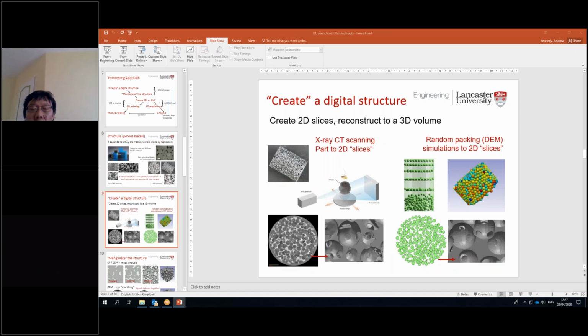So we can create digital structures in a number of different ways. What we found is a good approach is to use different methods to create 2D slices, which we can manipulate if we want, and then use that to reconstruct a 3D volume, which can be done in many different off-the-shelf software packages. So we can take actual samples, scan them using micro CT, produce slices, and then reconstruct those slices to produce a 3D volume. Alternatively, we can use a discrete element modeling method to produce a packed bed of spheres, and again slice that and reconstruct. And the reassuring thing here is that we see that actual real parts and our structures made from DEM models look very, very similar, which gives us confidence that these artificial packing models are pretty good replications of the real structures.